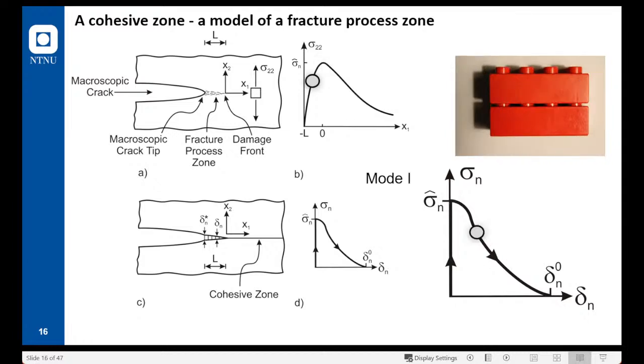Now, if we increase the load, the crack opens, as you can see here, but the stress does not drop to 0. This is a typical feature of a damage-tolerant material. And this position also here is somewhere inside the fracture process zone.